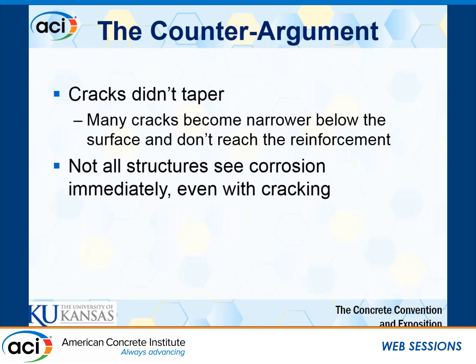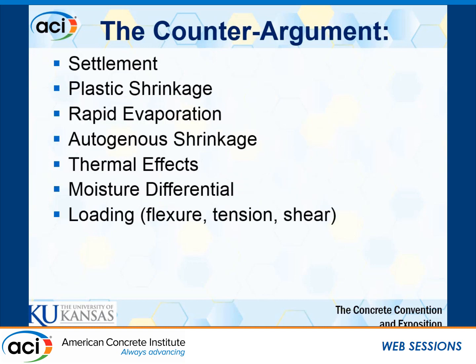And also, we don't necessarily see early initiation of corrosion, even with high degrees of cracking. A number of culprits that we're dealing with in cracking. We're focusing again on settlement cracking today as our early age cracking. There's also plastic shrinkage due to rapid evaporation. If we're dealing with low water cement ratios, we have autogenous shrinkage. If you're casting hot concrete on top of cold girders or vice versa, you may have to deal with thermal effects. If you have a big drying gradient, that can induce tensile stresses in the top of your concrete sections, and at early ages that can cause cracking.